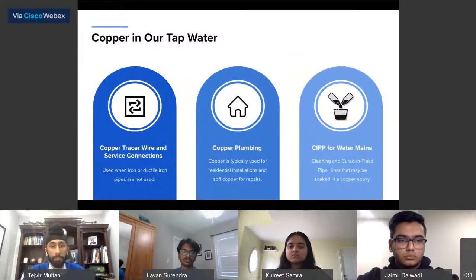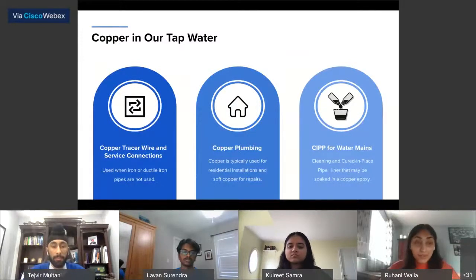According to several articles by the Government of Canada and the City of Toronto itself, most water mains are made of iron or ductile iron pipes, which we've mentioned. However, when these water mains are not made of ductile iron, copper tracer wire and metallic copper service connections are typically used. Depending on the environment, certain places require metallic copper piping as opposed to ductile iron or polyethylene pipes. And for example, that might look like residential plumbing.